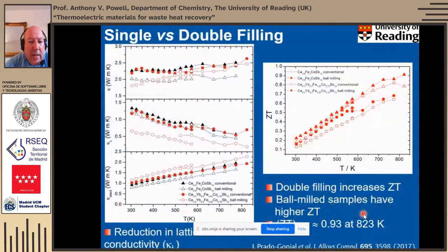So in terms of the single versus the double filling, what we can see here on these plots is the thermal conductivity, which is the key thing that we're really targeting. The triangles are the single-filled materials, the circles are the double-filled materials, and then for each we've got both the conventional and the ball milling. So the first thing to notice is that preparation by ball milling gives us a slightly improved, in other words lower, thermal conductivity, and also that the double filling is giving us a lower thermal conductivity than if we had single filling.